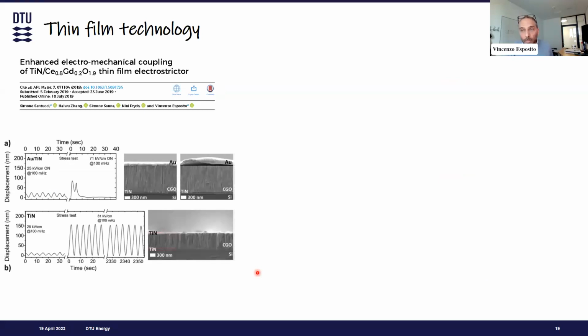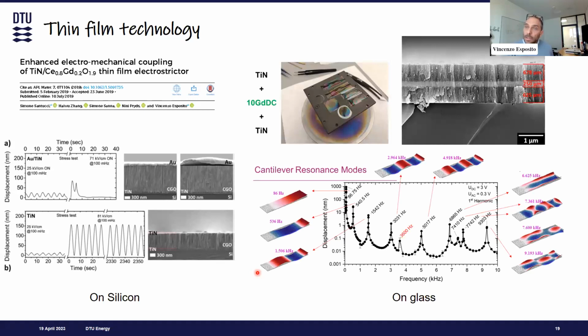The stability of the ceramic electrode is actually pretty important, and even superior to other metal electrodes that can be used in this technology. In this paper, for example, we show that gold is less mechanically stable than titanium nitride, and we get pretty interesting properties. Something else is the deposition at low temperature, because the crystallinity now becomes not that important. I don't know if you remember the first part about the grain size. We can still keep electrostriction even though we have small grains.